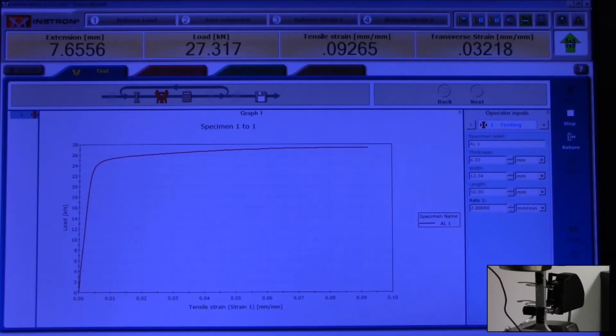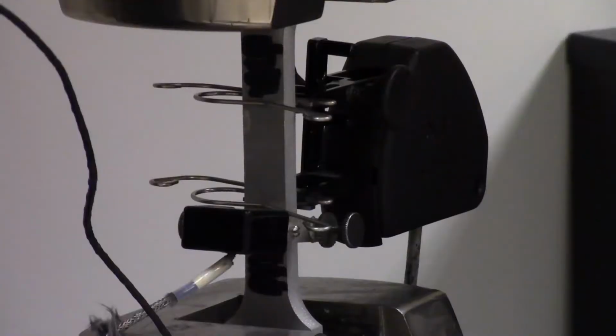So we're still plastically deforming fairly uniformly along the gauge section. Once we start to see that load drop, it means that the deformation is starting to be concentrated in a smaller region, and that's what we call necking. It looks like it's starting to drop now, so let's see if we can observe that.